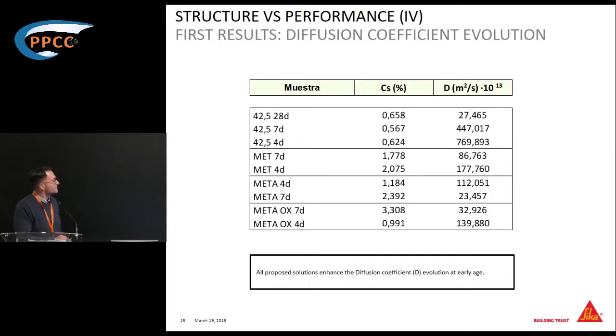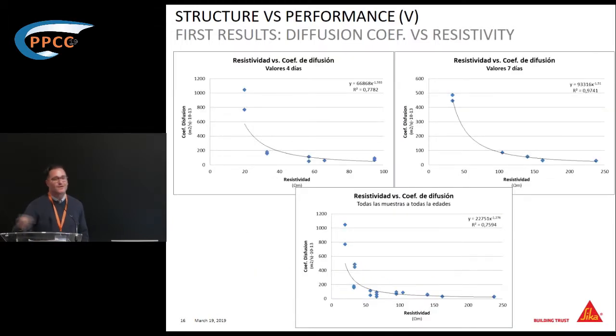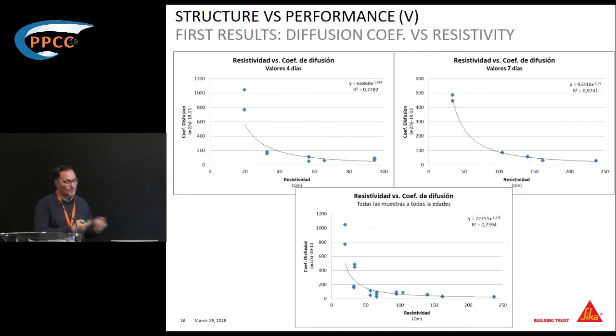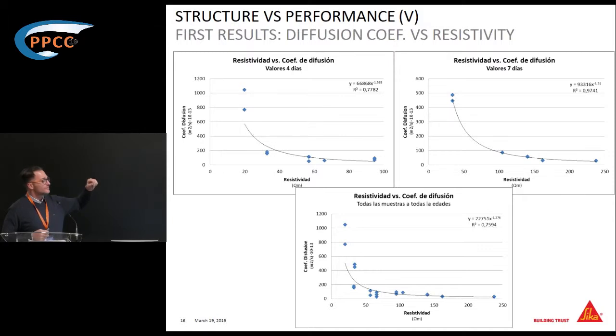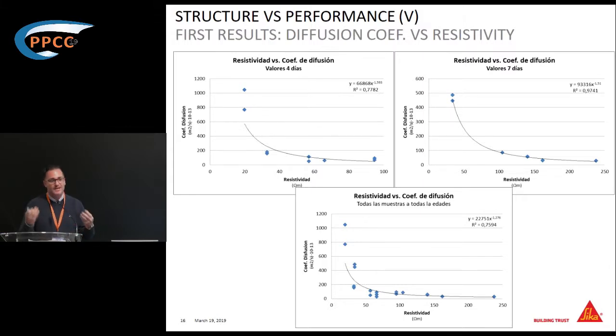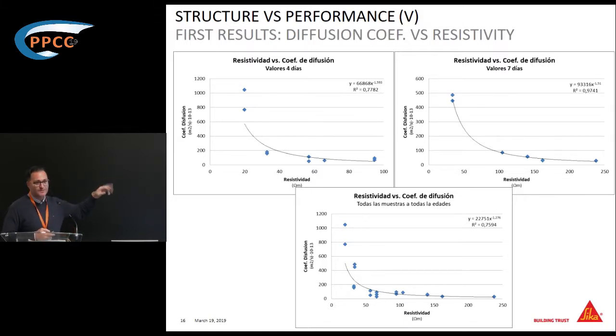We want to make sure all proposed methodologies are reliable. One key topic was to demonstrate that resistivity measurements at very early ages and the diffusion coefficient can correlate well, allowing us to build a kind of abacus using short-term, non-invasive, cheap, easy-to-implement testing — verified against real diffusion coefficients prescribed by authorities — to enlarge our testing portfolio.